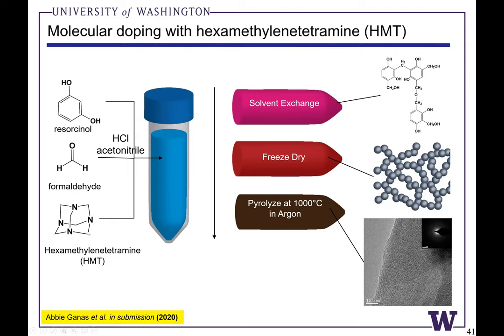And Abby chose a molecule, hexamethylene tetramine or hexamine, which is very nitrogen rich. So rather than calling our shot with the silicon split vacancy center, Abby wanted to demonstrate molecular control over nitrogen point defects in diamond. So it's a very similar process. We try to avoid silicon at all costs by using this sort of plastic reaction vessel.